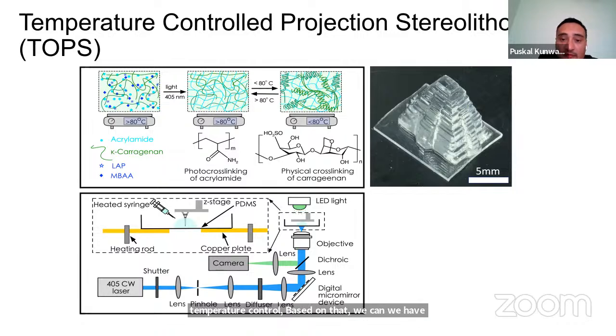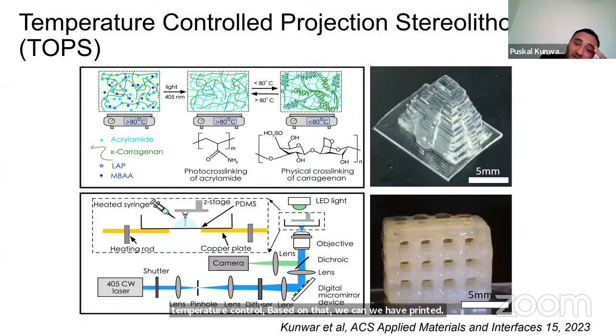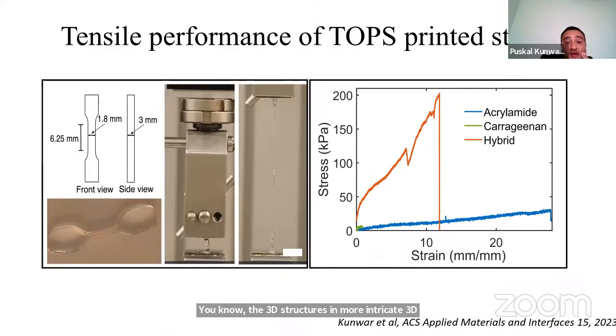more intricate 3D structures using this. Now in the tensile region, it stretches almost 11 to 12 times. The strain is 11 to 12 and the stress is around 200 kPa compared to its parent gel. It has way better mechanical properties, but we did see necking behavior in this one. We did solve the necking behavior by simply immersing the structure in a water bath.